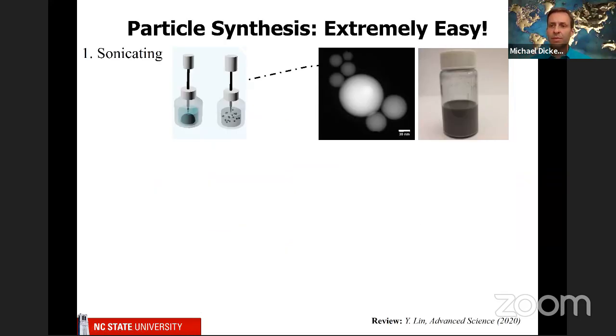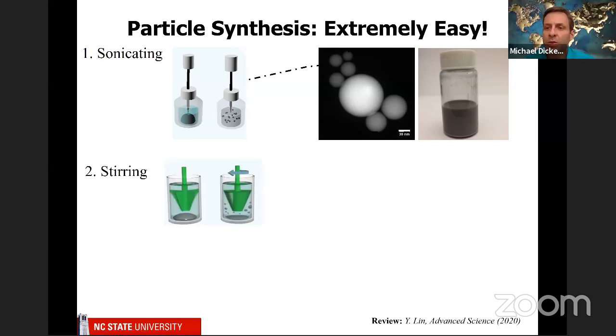And so I want to pause for 1 second. It's like a little commercial break here, but just to point out one of the really cool things about liquid metals, it's very easy to make particles. It really couldn't be any easier. One way to do it is to simply take liquid metal and sonicate it, just basically shake it, and it breaks up into droplets. They are very small, hundreds of nanometers, and this is a vial of liquid metal droplets, very easy to make. You can also stir it, so literally by hand or a high shear mixer, which Martin Thuo's group at Iowa State has been championing.